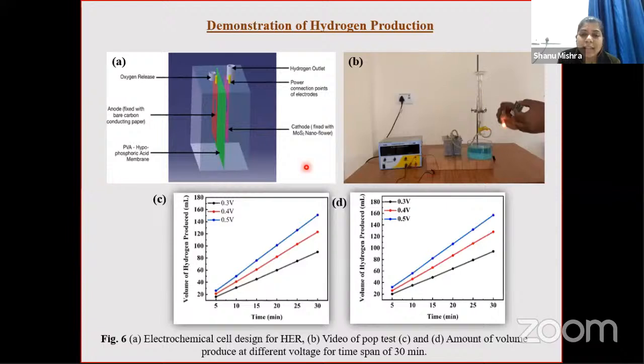Also we have plotted the amount of hydrogen produced by using both the CNTs in a time span of 30 minutes, and plotted the curve for different voltages. This is basically where we have optimized our coating, and this is on a 10 milligram coating of the electrode. After this, we checked the presence of hydrogen using the pop test.